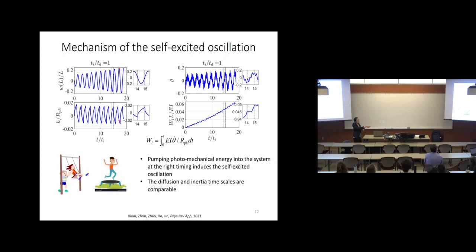So within this half period, the energy decreases but then increases. Eventually, it creates a net positive work done into the system. So that's why you are pumping energy into the system. This is because you see there is a phase difference. So that tells us that you need to pump photomechanical energy into the system at the right timing such that you can really pump energy into the system.